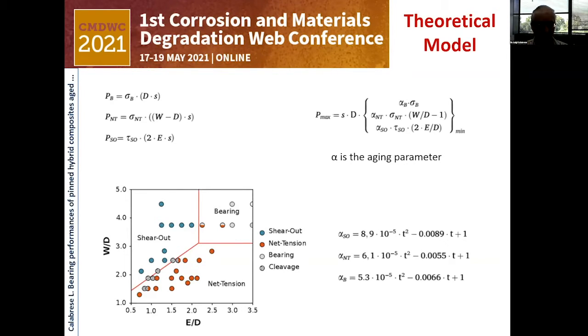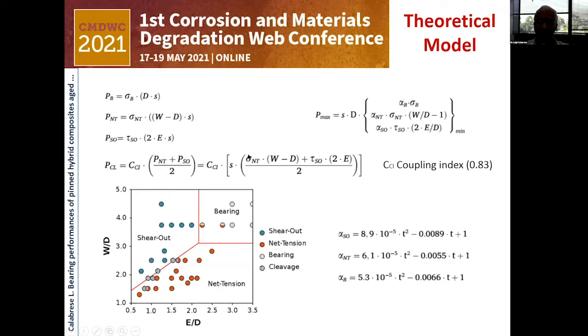What is the approach that we used? In particular, we started from our typical formula. These are the same formulas that I showed before, but now they are explicitated to the load. And we see that the maximum load, our hypothesis, is observed when we have the minimum from one of these formulas. But at the same time, we also added the cleavage contribution that is shown here, that previously I had not indicated. In particular, I considered the cleavage fracture as a mixed contribution of net tension and shear out. Therefore, I determined the average value, and then I considered a coupling index that experimentally was evidenced as 0.83.